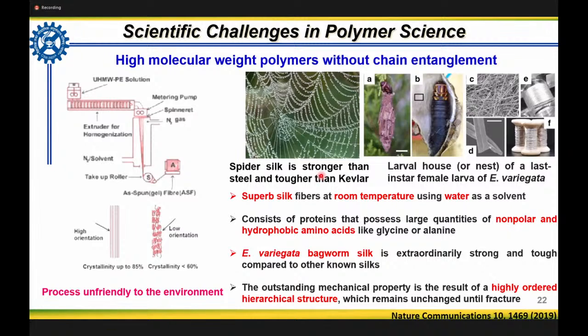So one of the greatest challenges is how we can process these high molecular weight polymers without the chain entanglement. For that, at the moment, we use the gel spinning method. In gel spinning, we have to dissolve the polymer in solvents like decalin or paraffin, spin it, and then the petrochemical based solvent has to be evaporated, again at slightly higher temperatures. So you can see what kind of environment we are creating. We are polluting the environment by evaporating large amounts of solvent to get highly oriented polyethylene fibers, and these can be very effectively used for bulletproof jackets.